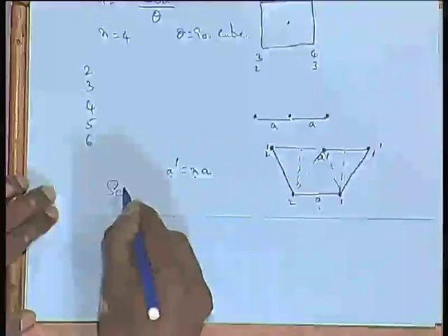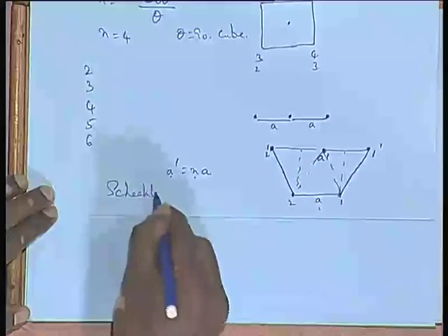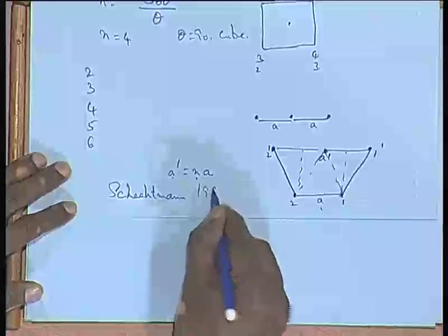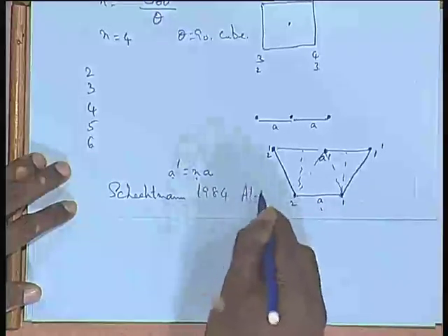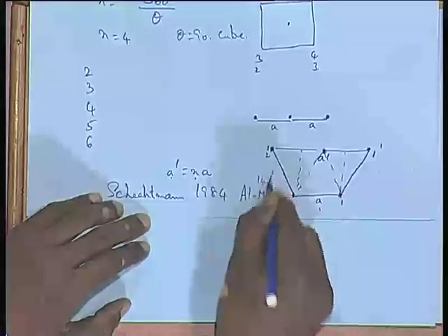1984, when a person by the name Shechtman, in an aluminum manganese alloy, aluminum with 14% manganese, made this alloy, rapidly solidified it, and then looked at the ribbon that you get in rapid solidification in a TEM, and he found that this shows an interesting symmetry.